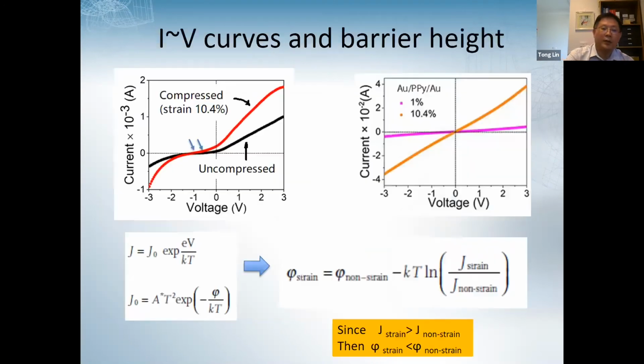If we test the IV curve, we can typically find a rectifier effect in the device, and under compression the rectification ratio increases. But for the ohmic device, made with gold electrodes on both sides, the IV curve looks just like a straight line, and under compression the current increased. This means the PPy conductivity is improved under compression.